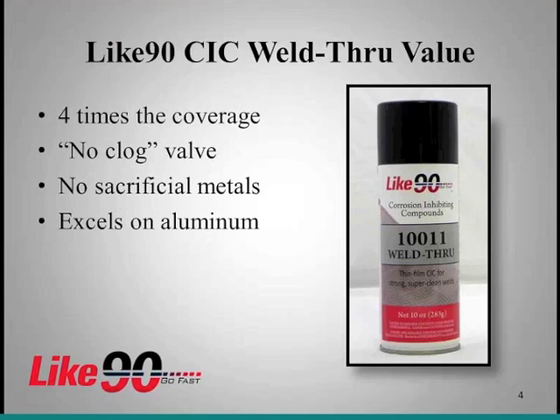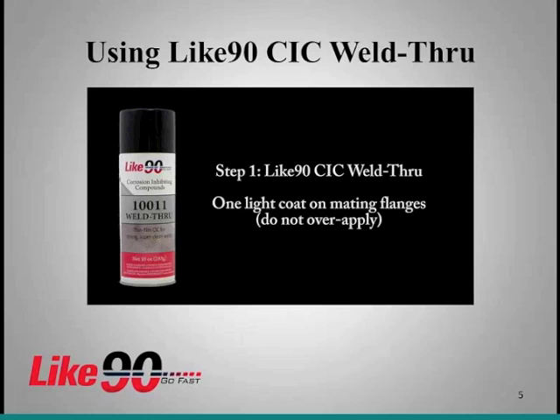As we stated in the aerospace industry, if you think back, I forget what year it was, but there was an Aloha Airlines where the roof had come apart on the airplane, and when they investigated it, they found that in their weld joints and their rivets, they had corrosion happening around those metals. And they had to come up with something different to overcome that corrosion, and this is the technology that they came out with for that. And what we found is this is a good technology that benefits the automotive aftermarket. So it does work on aluminum and steel. With the weld through, as we stated, it's one coat over top of it, allow it to flash.